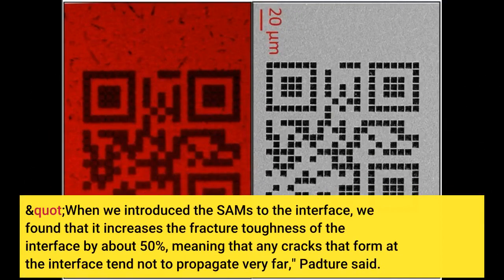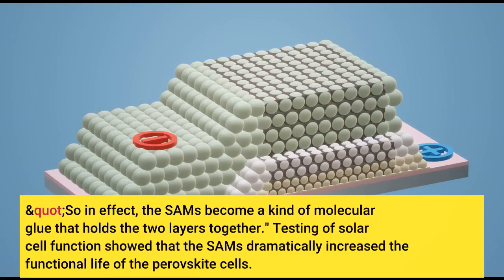"When we introduced the SAMs to the interface, we found that it increases the fracture toughness of the interface by about 50%, meaning that any cracks that form at the interface tend not to propagate very far," Padture said. "So in effect, the SAMs become a kind of molecular glue that holds the two layers together." Testing of solar cell function showed that the SAMs dramatically increased the functional life of the perovskite cells.